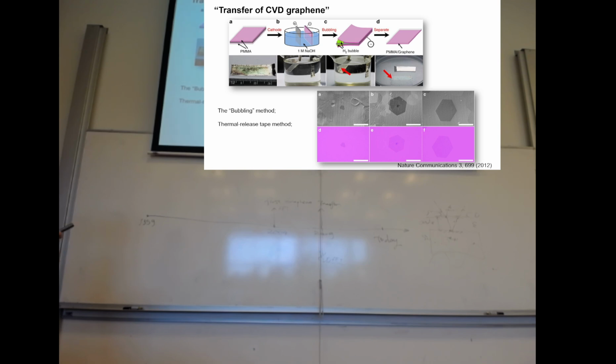And at the end, you will have this PMMA-supported graphene floating in your beaker, and you can just fish it out and transfer it onto any kind of substrate. Here is silicon oxide, before and after. You can see that the color is very homogeneous. Also, people found that using this thermal release tape can also help to transfer graphene. And that's a very important technique, because without transferring graphene from a metallic surface, nobody can do any kind of transport experiments. You cannot probe any kind of direct thermal behaviors like I will introduce later in the slides.